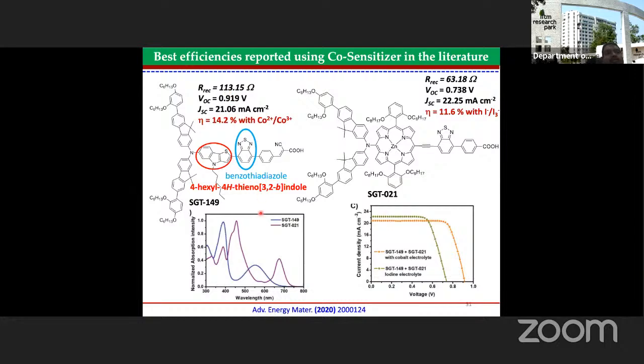So therefore, you see, this is the SGT149 dye, which is the blue one here, and SGT021 dye, which is a metal-based dye you see here. So together they kind of cover the entire solar spectrum from 300 to 800 nanometer. Therefore, more light can be harvested. You see the short circuit current density, generally it is around 15 milliampere per centimeter square; it has gone up to 20-22 milliampere per centimeter square, and the voltage with the cobalt electrolyte has gone near 0.9 volt for these particular dyes.